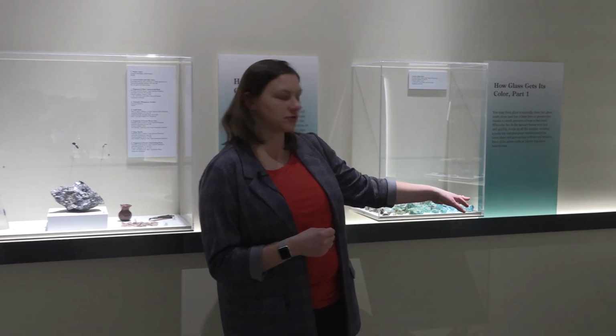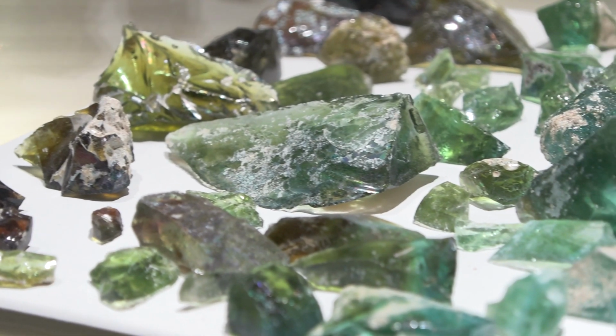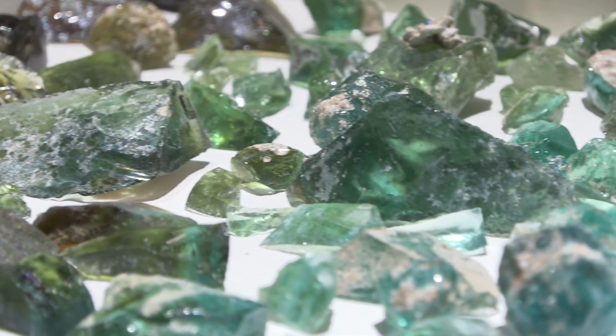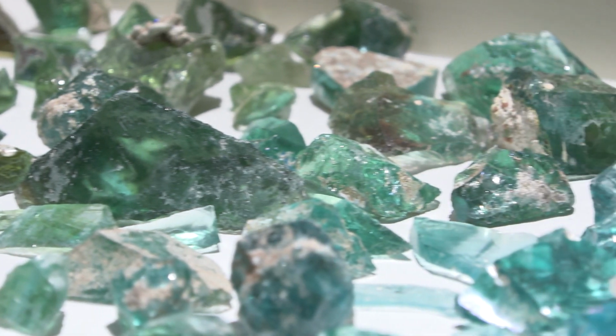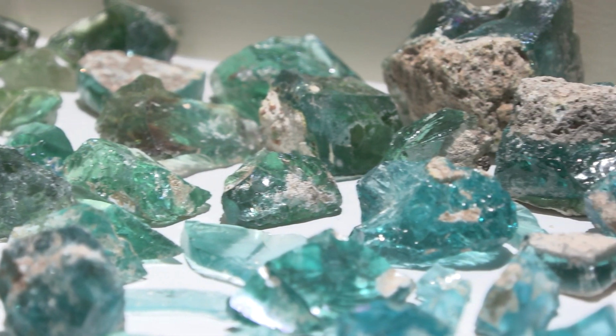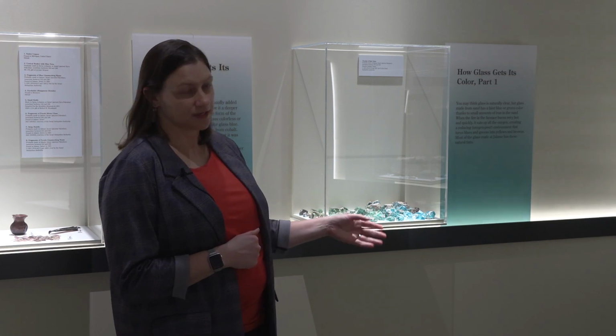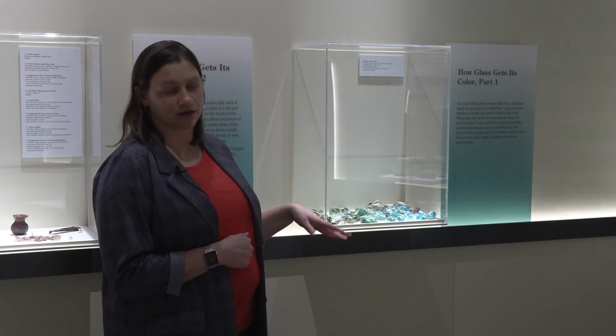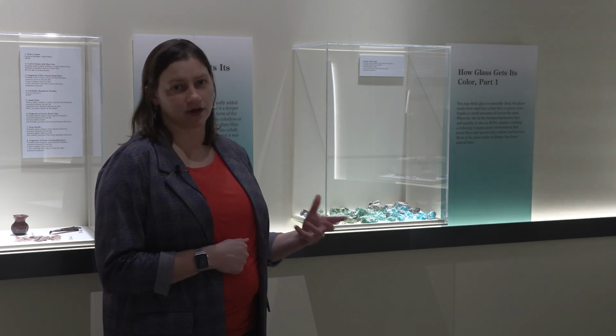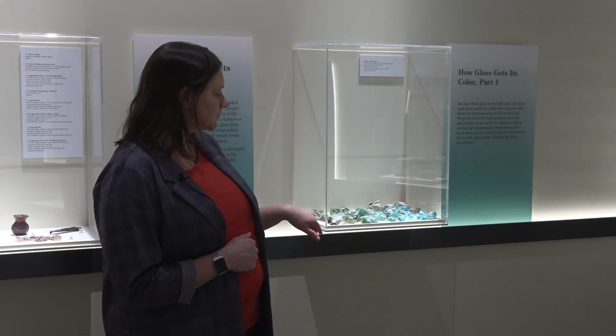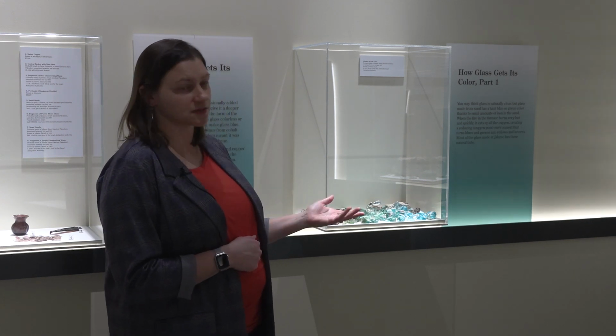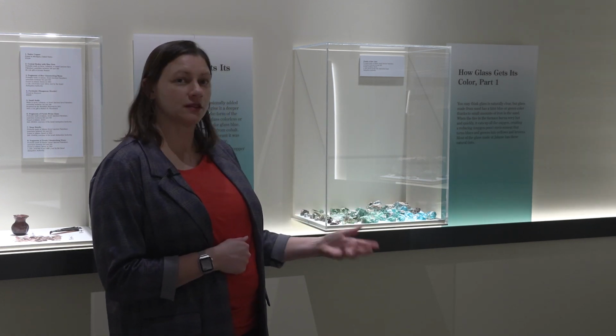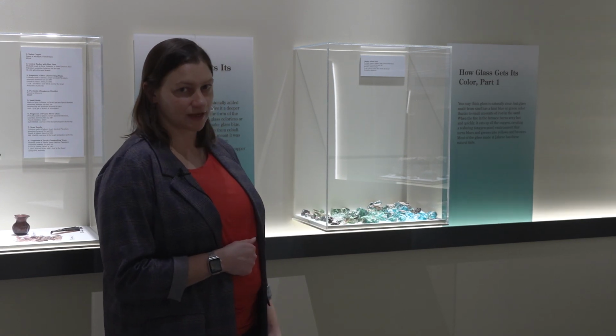So those basic ingredients that go into making glass, that sand and that mineral soda, create a lot of discoloration in the glass, like these blues and greens here. And that's what we call a naturally colored glass, and it's due to the iron that comes in, particularly with the sand, that reacts in the furnace and gives it these really beautiful blue hues, green hues, and then brown if that burning environment is a reducing environment, meaning there's not a lot of free oxygen available. So if you tested each of these pieces, you'd basically find them to have similar compositions. There's not different colorants or anything in them. It's all due to the presence of the iron in the glass.